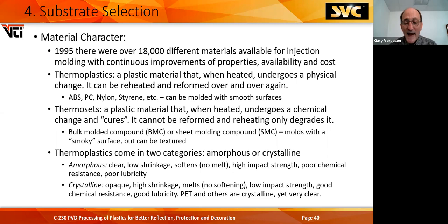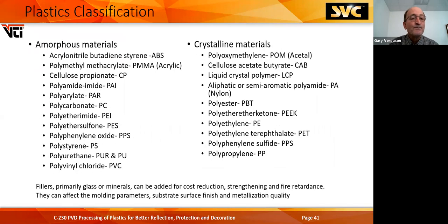Thermoplastics come in two big categories, amorphous or crystalline. Amorphous generally is clear, low shrinkage, softens, has high impact strength, poor chemical resistance, poor lubricity. Crystalline usually is opaque, has high shrinkage, melts, low impact strength, good chemical resistance, good lubricity. PET and other materials are crystalline, yet they're crystal clear, so they don't fit this opaque mold.